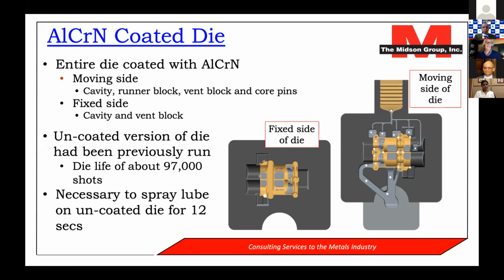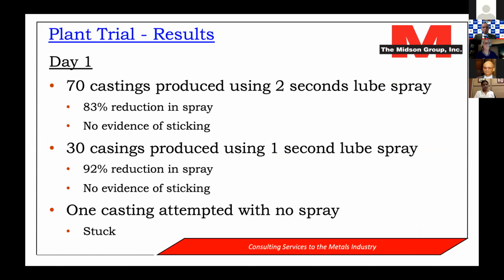What was nice about this die is that the caster that produced it had previous experience. They've been producing this casting for many years, and so they had experience with an old uncoated version of the die. And what they saw is that die had a die life of about 97,000 shots before it had to be replaced. And for the uncoated die, it was necessary to spray lubricant for 12 seconds.